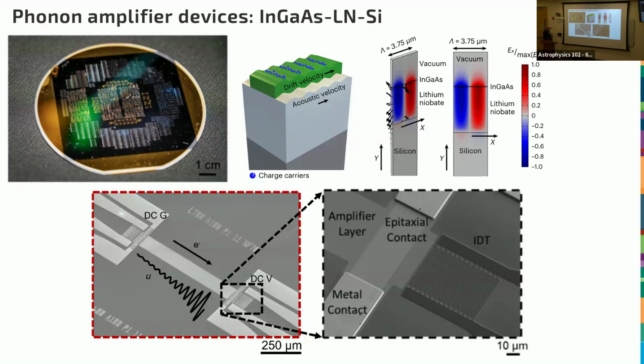Okay, and now you can see here these other materials. This is the amplifier layer. It's about 50 nanometers thick. We get about 70% of the mobility of the bulk materials. We get 7,000 centimeters squared per volt second. 50 nanometer film that's not even protected on the top. If you don't do semiconductor material, it's not very impressive, but it's kind of surprising that it worked that well.